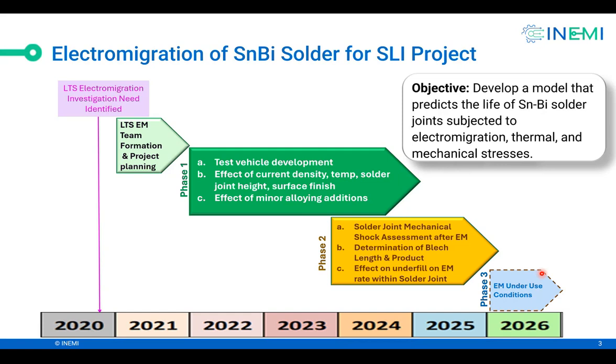And finally, phase 3, which is going to be next year, the electromigration. You see if we can get electromigration under use conditions. Most of the electromigration shown in the literature is with a very high current density and high temperature, which may not necessarily be the case for some certain applications like client computers. So that's what we are trying to figure out in phase 3. So really the objective here is to develop a model that predicts the life of bismuth tin solders when they are subjected to electromigration, thermal, and mechanical stresses. That's basically the objective here. Okay, you can go ahead, next slide.